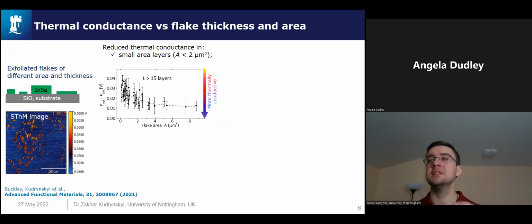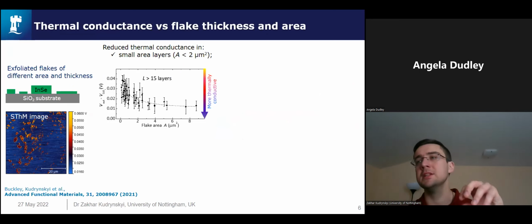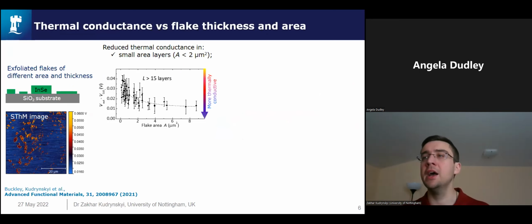To investigate the size dependence further, we systematically studied hundreds of flakes with different area, shown here in the thermal image. The plot here shows the SThM response as a function of area for samples with more than 15 layers. We can clearly see that the thermal conductance decreases drastically for laterally small flakes with an area of less than 2 square microns.